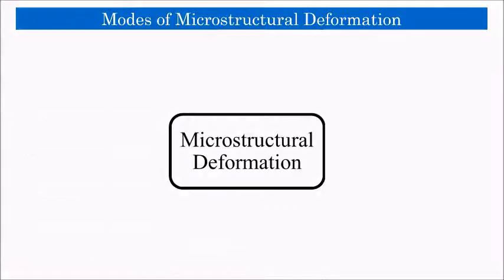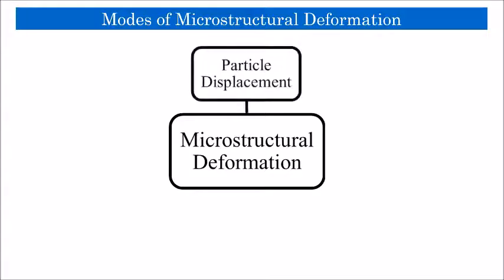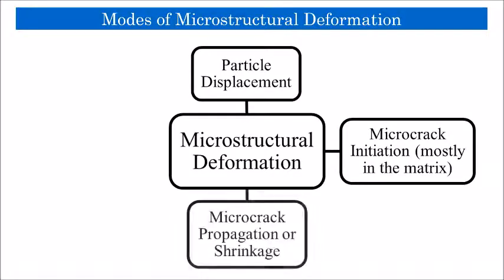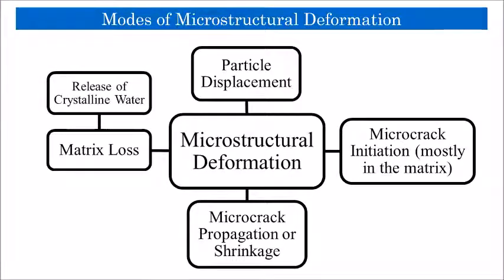Based on our SEM observations, we find that the thermal shock damage in these composites is best described as microstructural deformation, which can comprise particle displacement, micro crack initiation, micro crack propagation or shrinkage, and matrix loss, where matrix loss can be caused by the loss of crystalline water as well as micro-scale ablation.